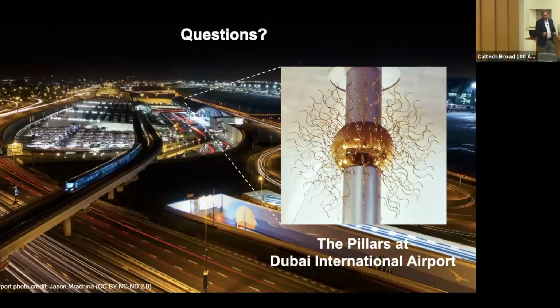Let me answer the first of these. These are not great electronic materials. They've got big distances between them. They've got oligonucleotides that have insulating end groups bound to them, and the distances are large. The system is really designed to modulate optical properties. They're ideal for modulating a lot of optical properties. For that reason, most of the targets that we focus on have been optical and catalytic. I didn't talk about the catalytic. We've done quite a bit on the catalysis front as well.